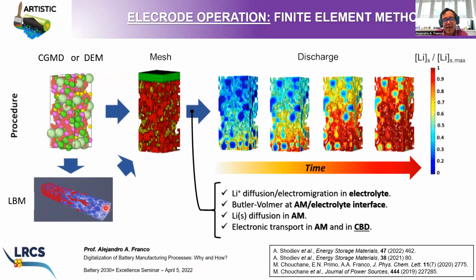And then the resulting microstructures, which consist of this spatial localization of active material, CBD, and electrolyte in the volume, can be meshed using our software to then inject the resulting mesh structure in a software able to simulate the electrochemical behavior of the electrode. In such a way, you can, for example, predict the lithiation or delithiation dynamics of your electrodes in 3D, by accounting for the physics going on in these electrodes, such as the transport of lithium ions in the electrolyte, the diffusion of lithium in the active material, the Butler-Volmer equations describing intercalation and deintercalation, and the electronic transport in active material and CBD, which means carbon binder domain, which is taken into account explicitly in all this modeling workflow.